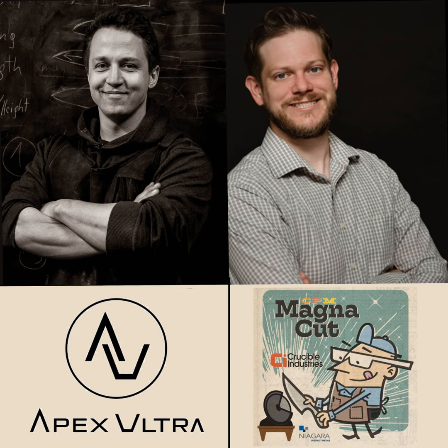And once you have your theoretical optimum, if you have your simulations and your designed composition, then you go and make a small laboratory melt. So that was in fact a vacuum induction melt. So that was the process that I was speaking about earlier. So in the laboratory testing, we had a vacuum induction melting, not an electro slag remelting process. And now you're only talking about 10 to 20 kilograms. But the steel is still going to behave similar to what you're going to have if you scale the process up. Just a little different.